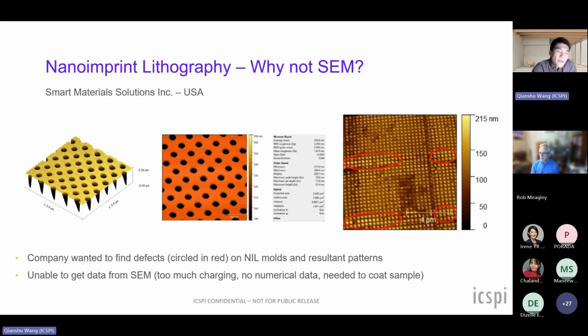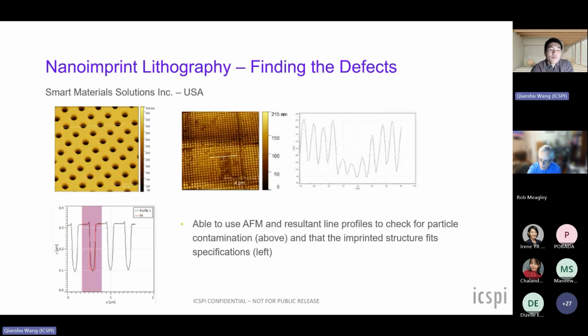And continuing on, same thing. This company wanted to find defects. They were circled in red on the image on the right, on their NIL molds and some of the resultant patterns. The reason SEM wasn't working for them is that they were seeing too much charging. They couldn't coat their sample. They weren't able to get numerical data as well. So here we were able to use AFM, and we're able to pull out these line profiles. Whenever you take a 3D AFM image, you're able to draw lines across that scan and receive 2D line profile information that you can carefully look at yourself to check for specific metrics that you're looking out for. So in this case, we're looking for particle contamination and that the imprinted structure fits the specifications as shown on the left, or let's see particles on the mold as well.